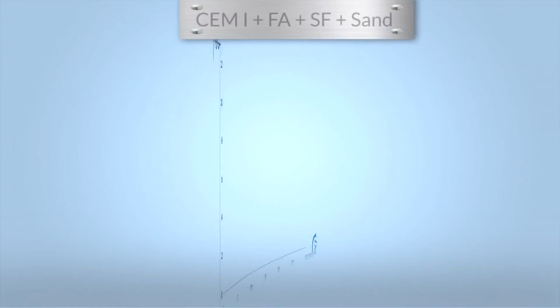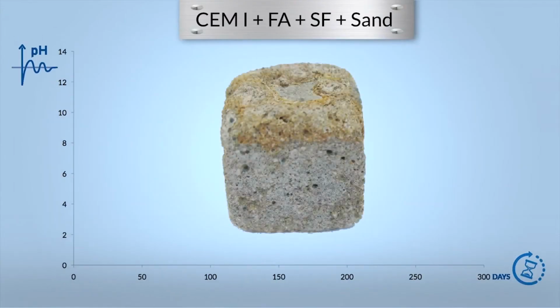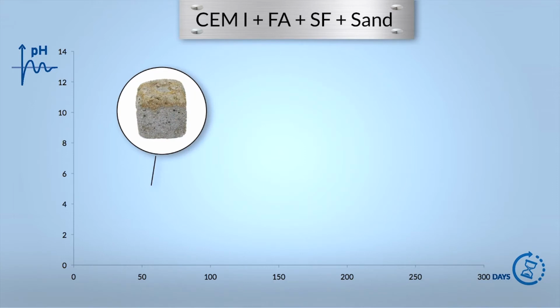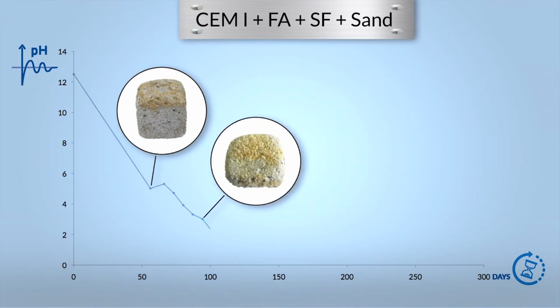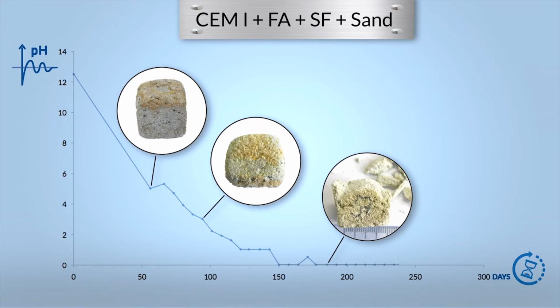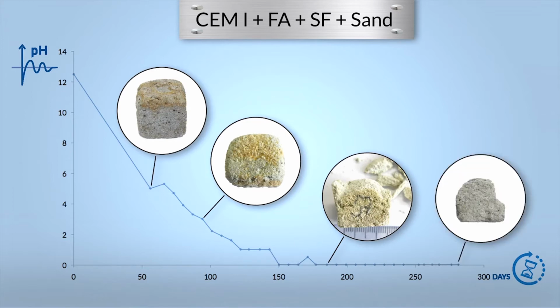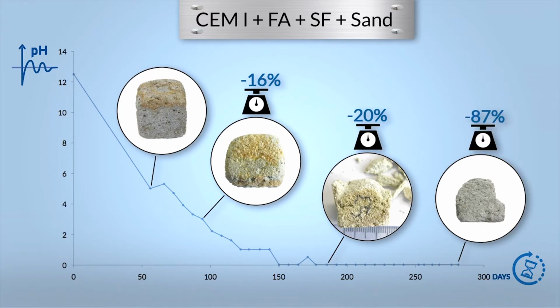This second set of specimens has been made with the same OPC CEM1 with the addition of fly ash and silica fume. Although such additions are expected to improve concrete durability, it does not enhance protection against H2S biogenic corrosion. Once again, the pH decreases below 1 within a few months, and severe damages are observed. The weight loss after 9 months is 87%.